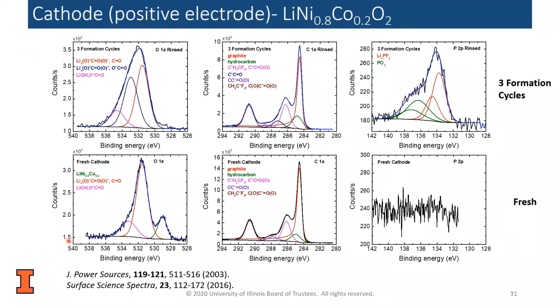And then by looking at the change in chemistry, we could see that the metal oxide peak is pretty much attenuated. So we have a nice, fairly thick coating, at least in terms of electron emission, fairly thick coating consisting of carbonyls and carbonates. And then we also see that there is an increase in the phosphorus signal. So in this electrode, the electrolyte is what's known as lithium hexafluorophosphate, or LiPF6. And so we're seeing that it is actually deposited upon the oxide as well and participating in the SEI layer.